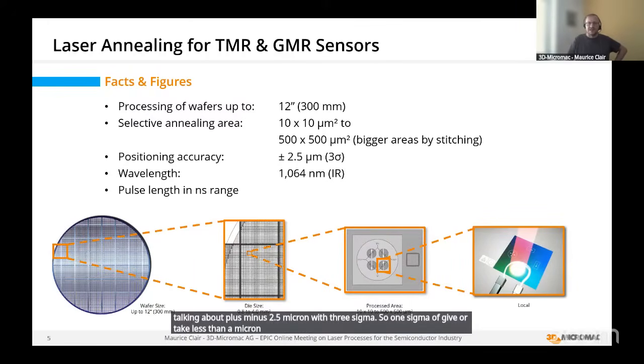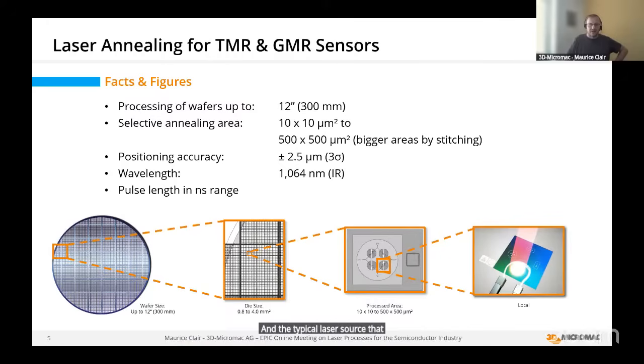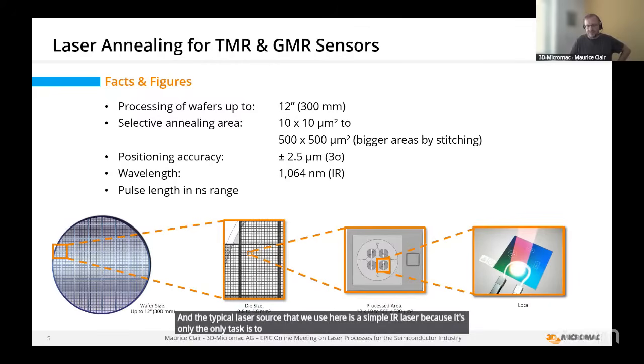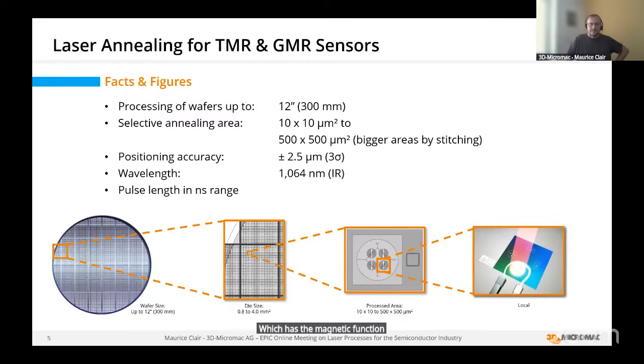And the typical laser source that we use here is a simple IR laser, because the only task is to locally heat up the material, the volume. Those layers are typically deposited underneath the surface. So you don't want the surface absorption, you want to absorb in the actual metallic layer, which has the magnetic function.